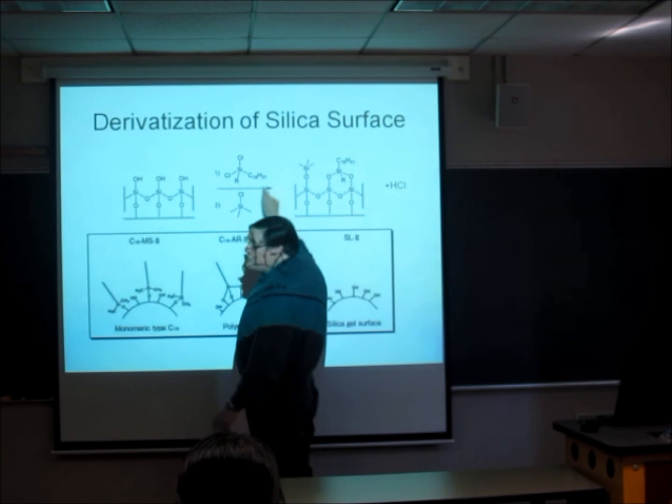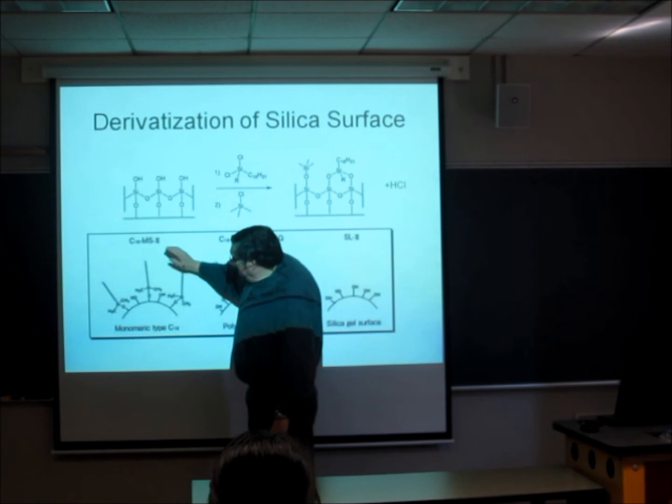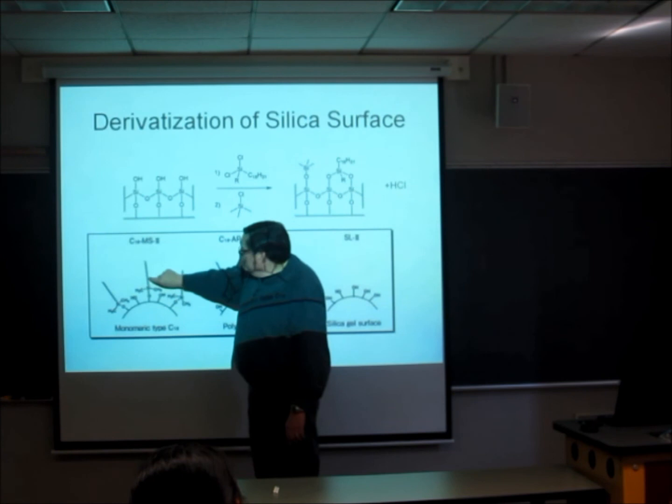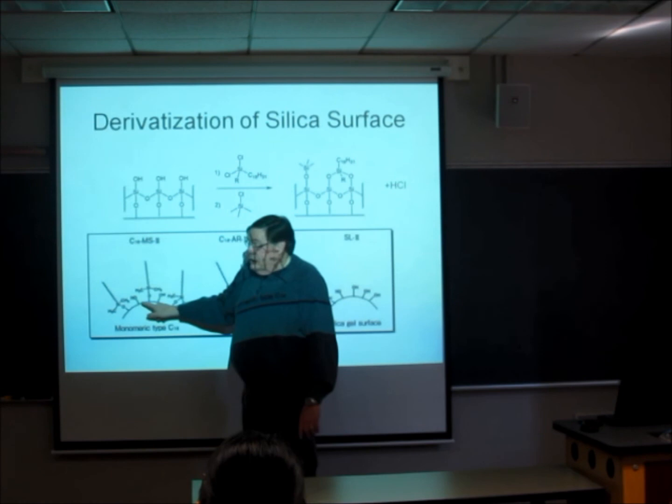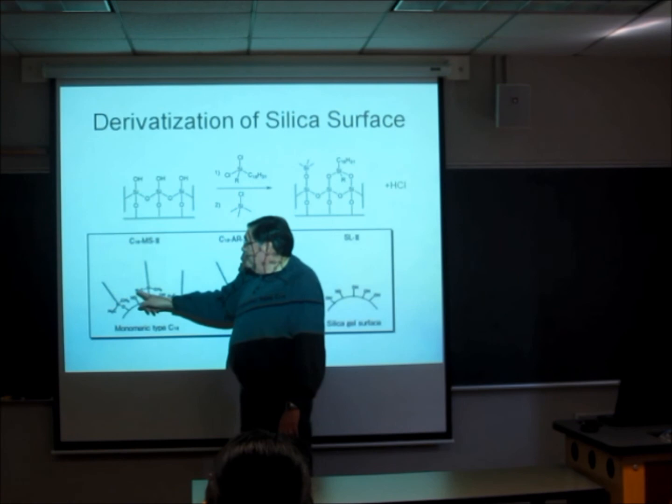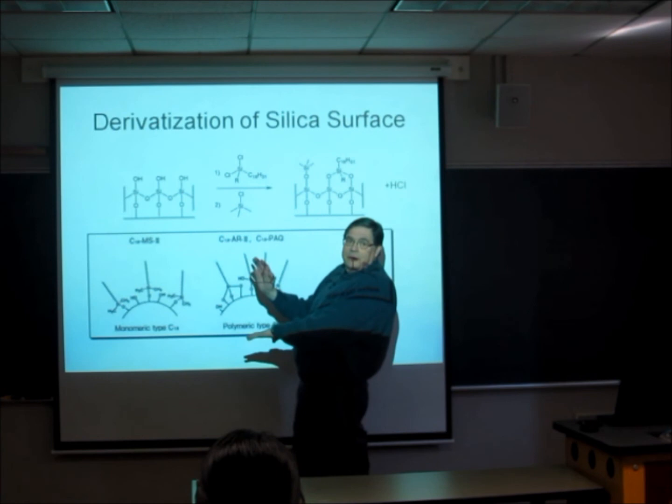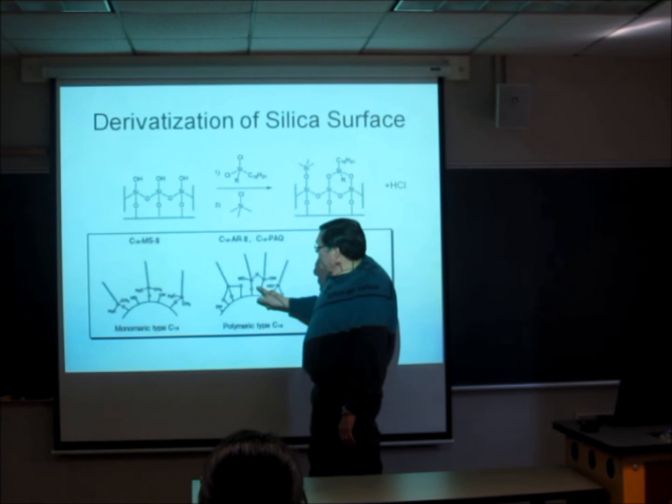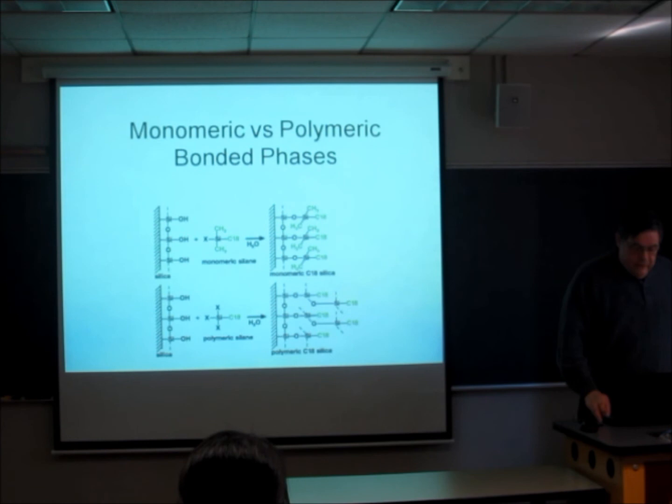You'll be left, this shows the main reaction is the silane with an 18 carbon long chain. That's a real oily long chain, real low polarity. Here it shows these things sticking out into a low polarity solvent. And you have these sites, OH, that have not reacted with anything. These are low polarity sites now. And solutes that have low polarity will try to cling to these. But what happens down here? These are high polarity sites. So these sites can cause you trouble. One of the things they can do is they can be a site of attack for base hydroxide. And this can dissolve away. At least the size is not right. They're disproportional.